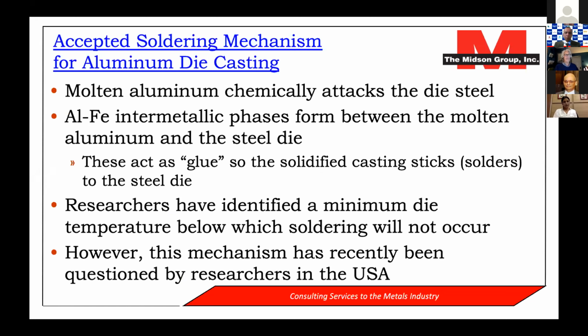There have been several papers over the last 20 years or so providing the mechanism for soldering. Back in 2000, Shankar and Apelian gave a 6-step mechanism for soldering of the aluminum to the steel. They said initially the molten aluminum chemically attacks the die steel, mostly at the grain boundaries. And then we get formation of an intermetallic phase between the molten aluminum and the steel die. So the aluminum forms a compound or an intermetallic phase with the iron from the steel. And this phase acts as a glue so that the solidified casting sticks and solders to the steel die and makes it difficult to eject.